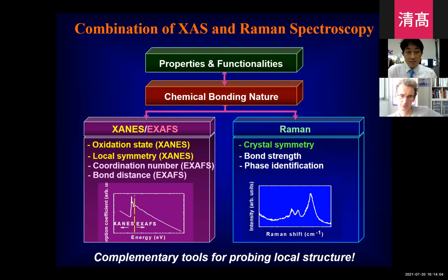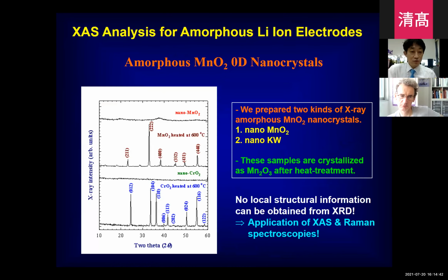So we frequently combine the XAS and Raman because the XAS can give valuable information on coordination number and bond distance. Even if you have very nice XAS data for long distance, we can specify the crystal symmetry by fitting with the multiple scattering factor, but frequently it is not possible. But the Raman is very, very sensitive to the crystal symmetry. So if you combine both, then you can specify the local crystal structure of nanostructured materials. Let me show you one example.